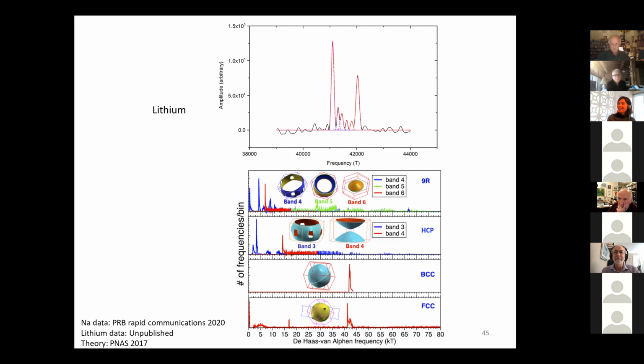Let me add that there are some codes and approaches that have been developed, and it's quite important for the hydrides, for example, where the quantum effects are large. These approaches attempt to do it self-consistently. So it's like a self-consistent phonon calculation, but with the quantum zero point. And it's working fairly well for some systems. Nice papers out of the group in Spain using this method. Yeah, I think we're on the edge of doing it. But I think these are extremely important to take into account when we are looking at these very light systems, hydrogen, lithium. Yeah. Thank you.